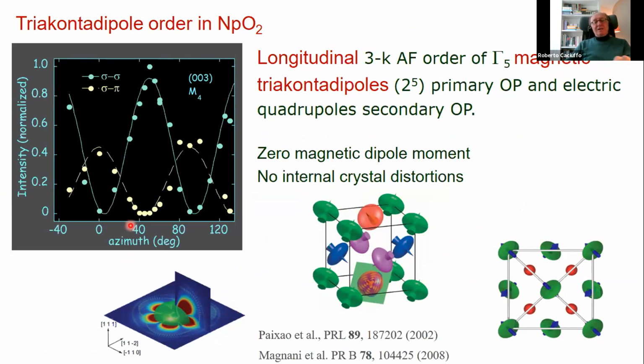resonant X-ray diffraction experiments, essentially measuring superlattice reflections corresponding to some order, an analysis of the polarization channels, here sigma-sigma channel and sigma-pi, that is incident and final polarization perpendicular to the diffraction plane, or perpendicular and parallel in the case of the white points, and the modulation of the intensity as a function of the azimuthal angle, reveals that the secondary order parameter are electric quadrupoles of gamma-5 symmetry, forming what is called a triple-k longitudinal order. The primary order parameter can be established by combining this observation and inelastic neutron scattering, and the result is that it is a rank 5 magnetic multipole.